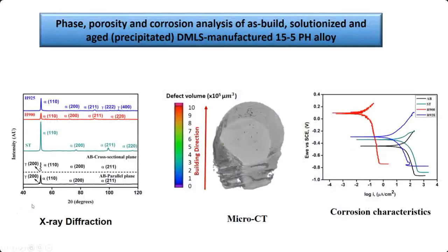And we did the XRD studies for all the structures - the as-built structure, the solutionized one, as well as the aging treatment at two different temperatures and times.